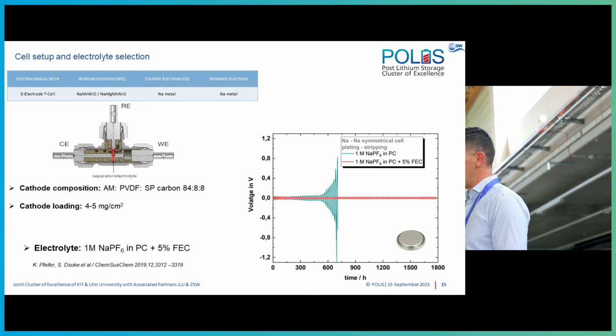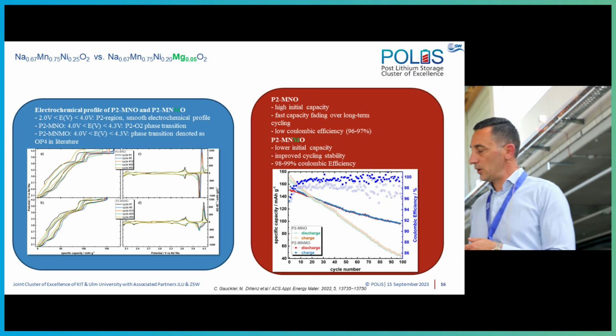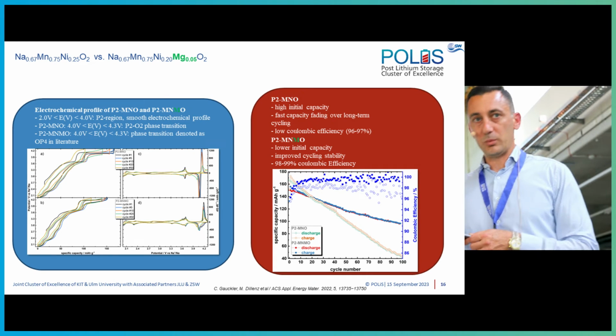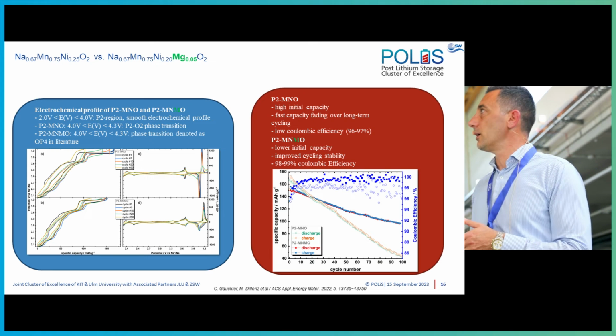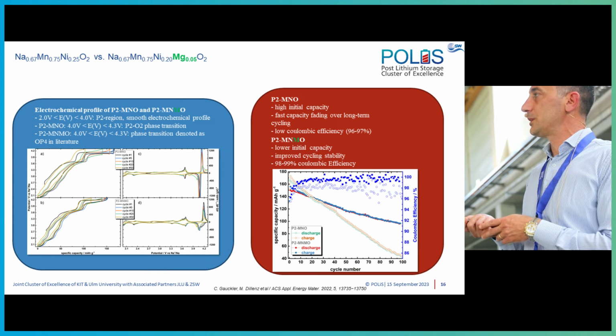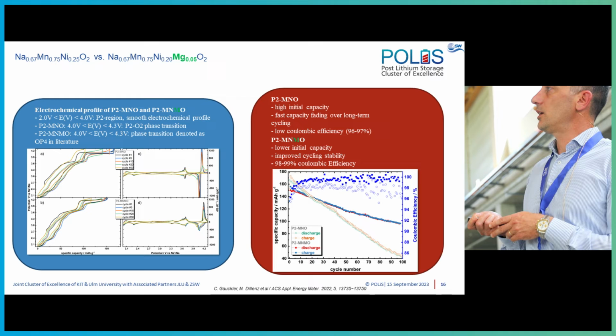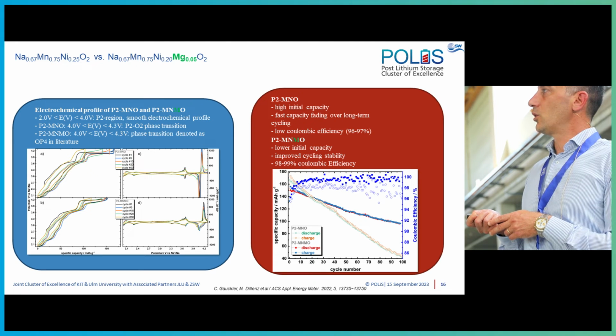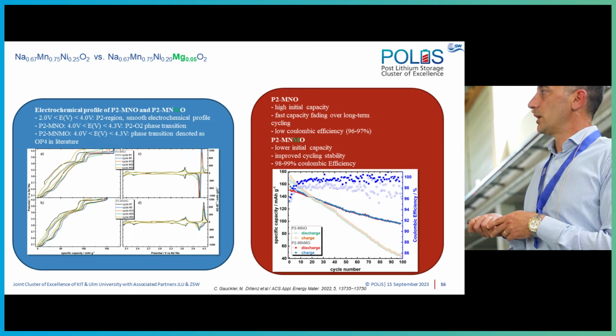We went into electrochemical characterization, as I said, the 3 electrode cells. Now, if we look at the difference between the two materials, so the doped and the undoped, what you can see here, you have a very long plateau, yeah, a very flat plateau, and this is also reflected by a very sharp peak in the differential plot.